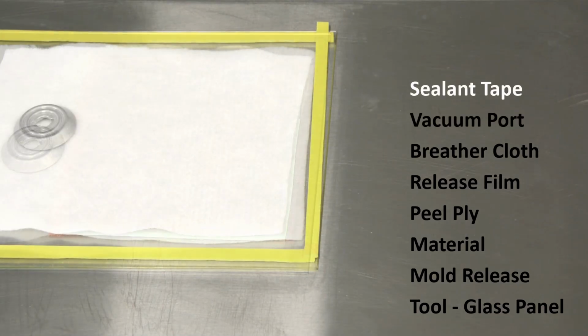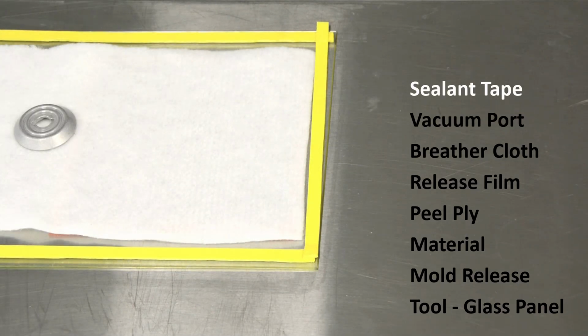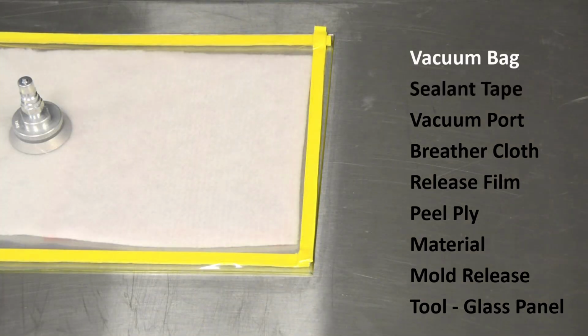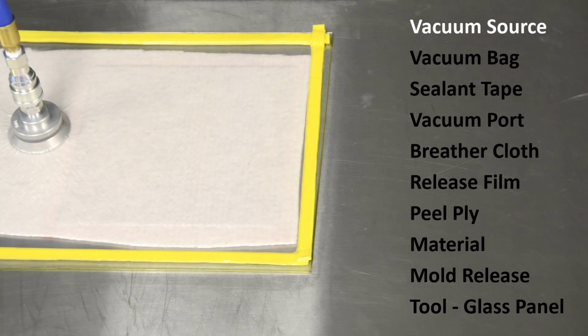We will now place sealant tape, also called tacky tape, around the edge of the tool. This tape creates an airtight seal between the tool and the vacuum bag. The vacuum bag gets placed over top of the layup and forms an airtight seal around the part. A hole is made for the vacuum port and a vacuum pump is connected to evacuate the air from inside the layup and produce consolidation pressure.